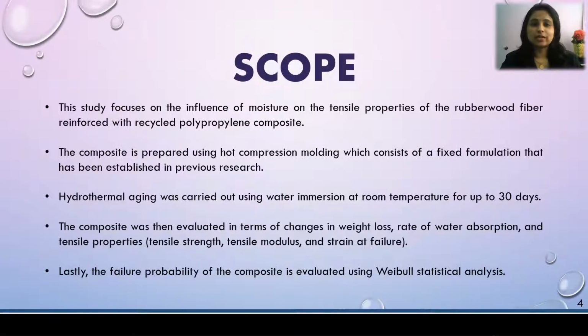The study focuses on the influence of moisture on the tensile properties of the rubberwood fiber reinforced with recycled polypropylene composite. The composite is prepared using hot compression molding and consists of a fixed formulation that has been established in previous research. Hydrothermal aging is carried out using water immersion at room temperature for up to 30 days. The composite then was evaluated in terms of changes in weight loss, rate of water absorption, and the tensile properties, as in tensile strength, tensile modulus, and strain at failure. Lastly, the failure probability of the composite is evaluated using Weibull statistical analysis.